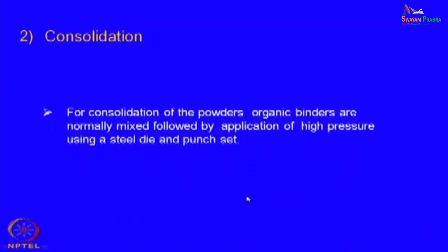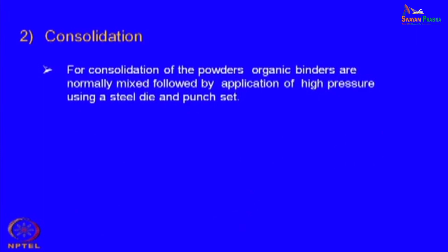Then the next thing is, once you have the powder composition, you have to consolidate. That means you have to give it a shape. The shape is done, the consolidation, the powders normally are mixed with some organic binders. In ceramic terminology, green means without fire, which has not been heated. At room temperature, whatever you do is actually green processing, and the shapes which you get at room temperature are called green ceramics.